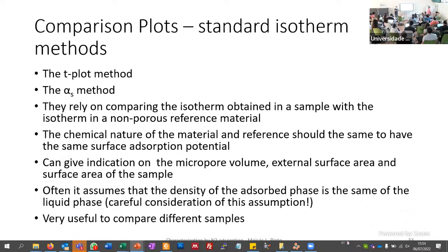Yes, so a material where you don't have pores. So we are going to compare your material, which has pores, with a material that doesn't have pores. So the chemical nature of the reference material and your material that you want to study should be the same. But this is quite often very difficult. Nevertheless, you can say, okay, I use this standard isotherm.